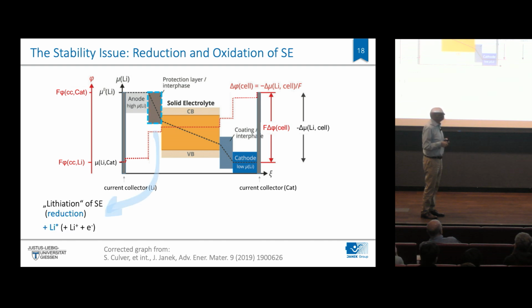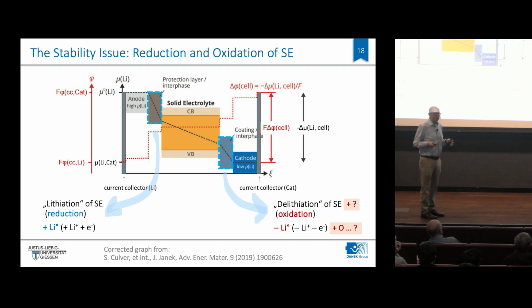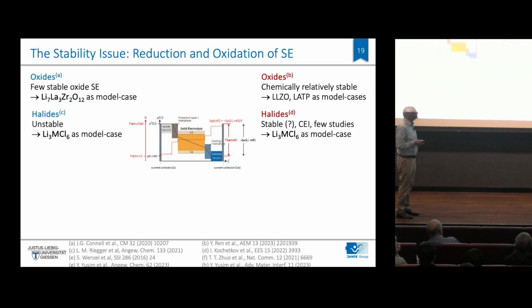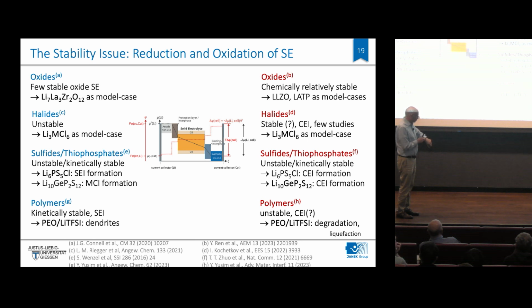that at the anode side, typical solid electrolytes may easily be reduced. At the cathode side, they may easily be oxidized, and you have a lot of degradation reactions. So one of the major issues in solid-state batteries is really the degradation of the electrolyte and the lifetime, which I think still is, by and large, an unsolved issue. And we looked into that. I will move past that quickly: all the different types of electrolytes all have their stability issues.